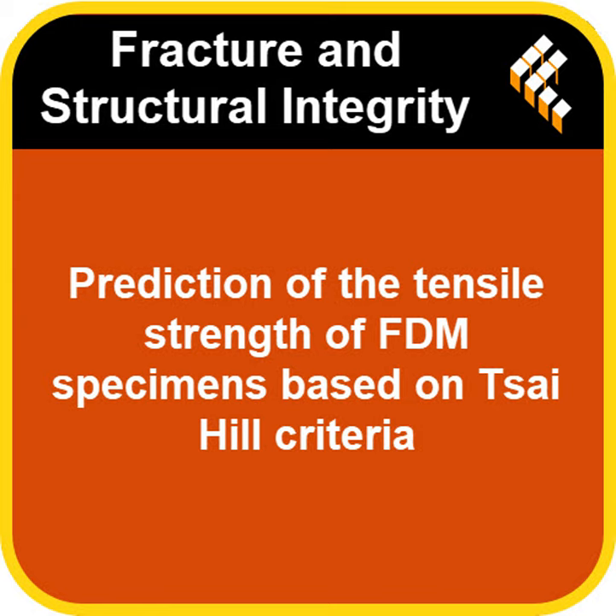0, 45, 90. Makes sense. And they also made sure the inside of each part was completely solid, what's called 100% infill. That's key for ensuring good adhesion between the layers. No gaps inside. Right. Then they compared parts made like that with and without a contour. The contour is like adding a couple of extra very thin outer layers. It gives a smoother finish and, as we'll see, potentially adds more strength. Okay, so different internal grain directions and with or without that smooth outer finish. Got it. So how do they actually test the strength?